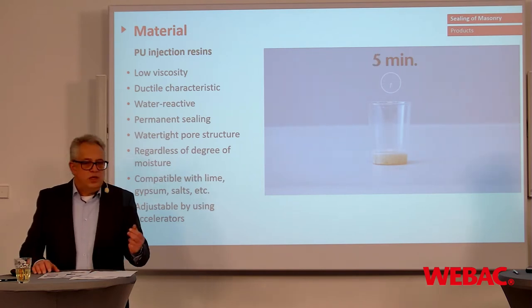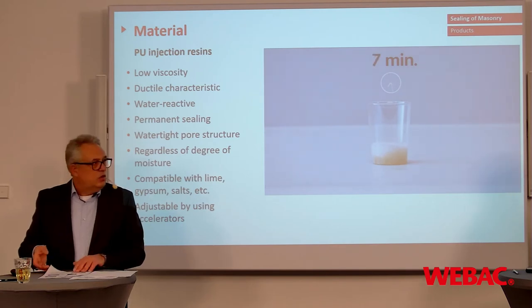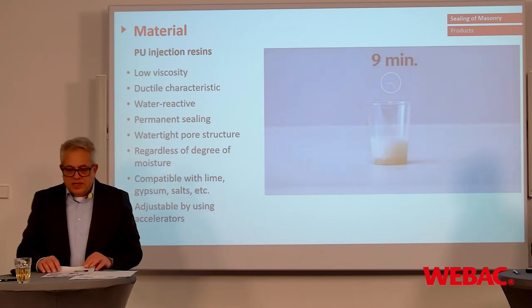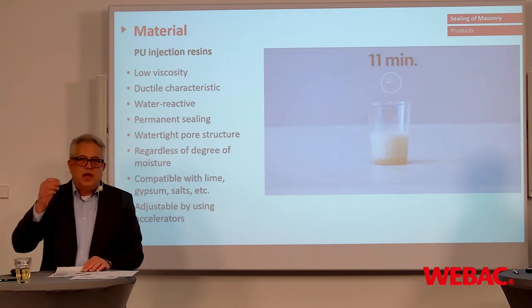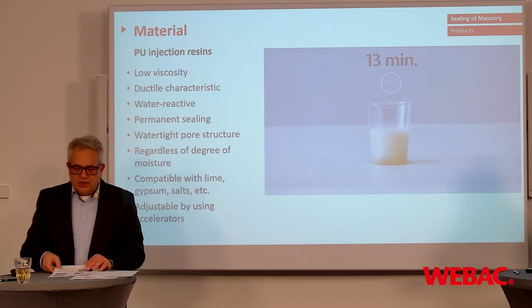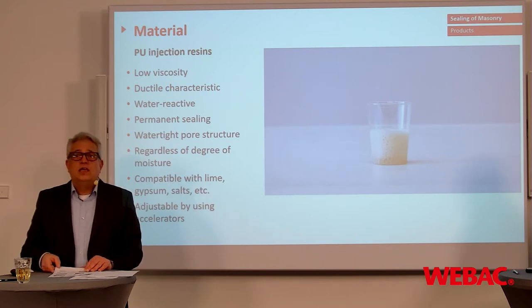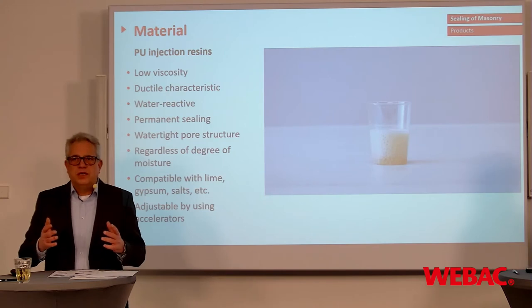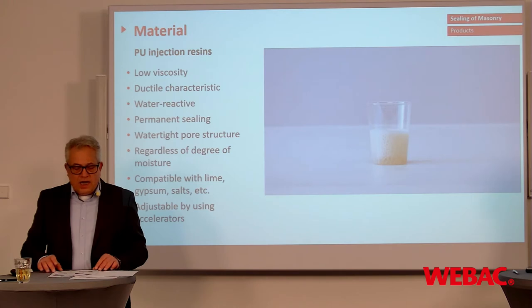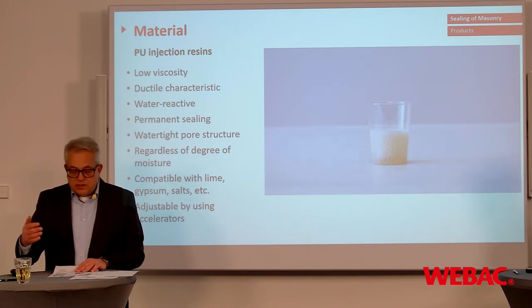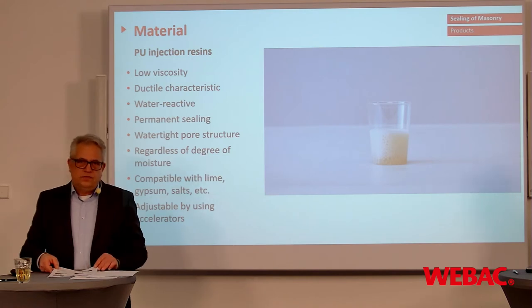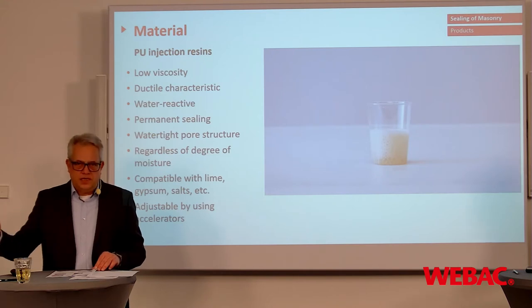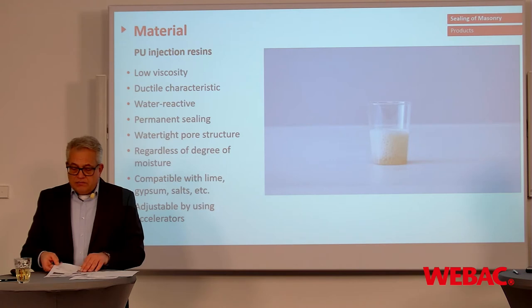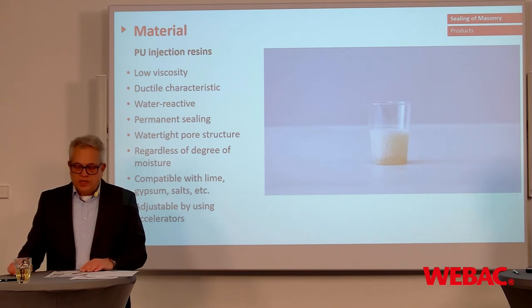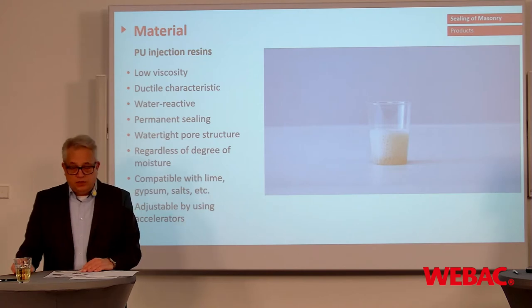The viscosity, we have different kinds in our product range. It starts from 30, 40 millipascal seconds. To have a comparison, water has one and honey, in general, roughly 10,000. Again, they have a ductile behavior, so it's possible that they also take movements after the injecting. They are water reactive and they are a long lasting and permanent sealing. They have a watertight cell formation, and you can use them in combination with more or less all materials.